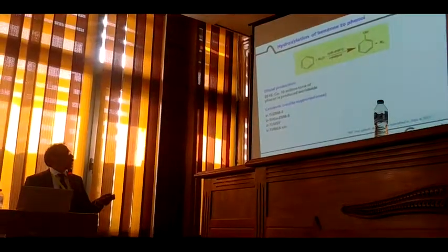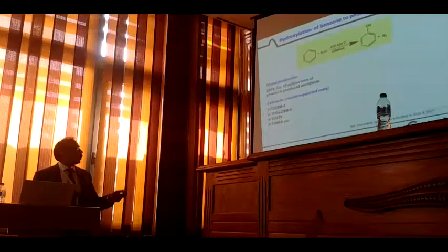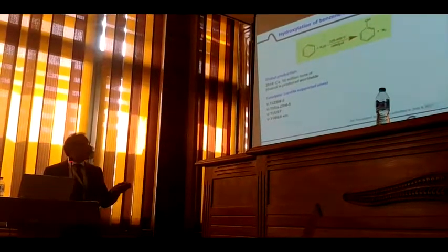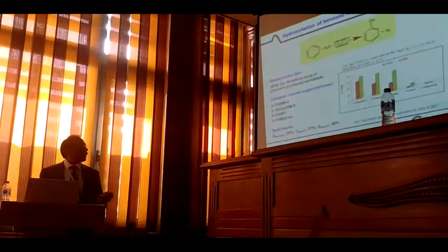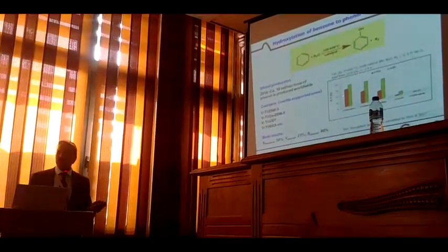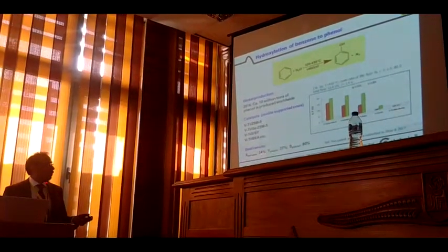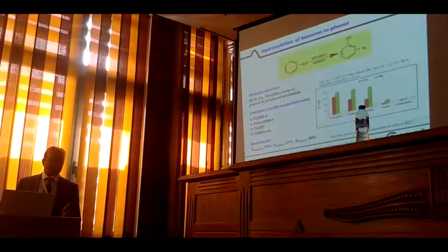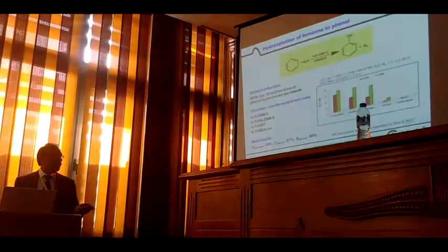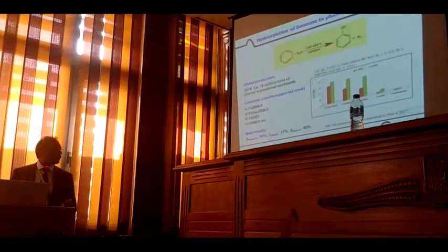About 10 million tons of phenol is produced worldwide. We use different zeolite supported metal doped catalysts, and from the best case we reached nearly 27% yield at 33 to 34% conversion of benzene, which is the best result reported so far. We also submitted two patent manuscripts last year and before that. They are not published yet.